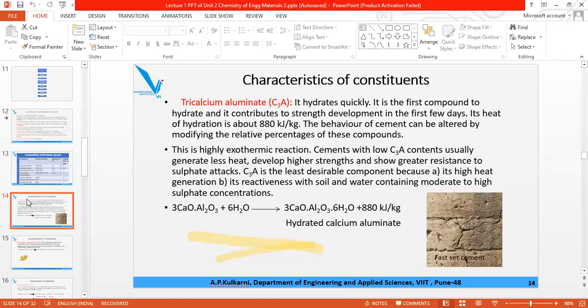In low quality cement, the C3A percentage is very high. Because of that, the heat of hydration is high. This type of cracks are developed in construction work. These are hairline cracks, and if they come together, they merge into a small block, and if it is observed at the bends, joints, etc., then the whole construction work collapses. Therefore it is desirable that C3A should be as low as possible.